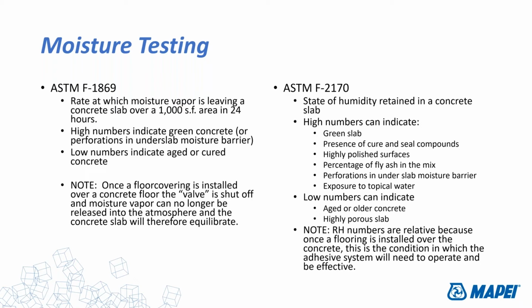The ASTM F1869 is perhaps the older, more traditional method for determining moisture vapor emission rates. This is what we call the calcium chloride test. This is the little petri dish of calcium chloride that we put underneath a plastic dome, and you let it sit there for 3 days on top of the concrete slab, come back and record the measurements. And that gives you a number that says at what rate the water is evaporating out of that slab over a 1,000 square foot area over a 24 hour period. So this really is giving you rate of evaporation information.